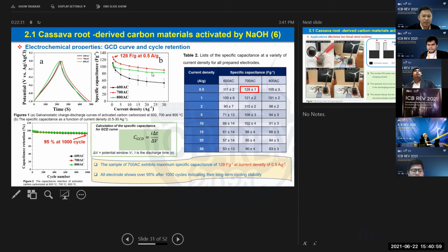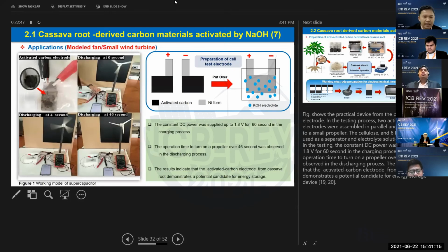And so we try to sort out why this temperature is the best condition for the preparation of the carbon-based material that gives the highest specific capacitance. And one of my students also tried to use the prepared material for the fabrication of a simple model fan, or small wind turbine, and it works. So this confirmed that this activated carbon electrode from cassava root can be a potential candidate for energy storage application.